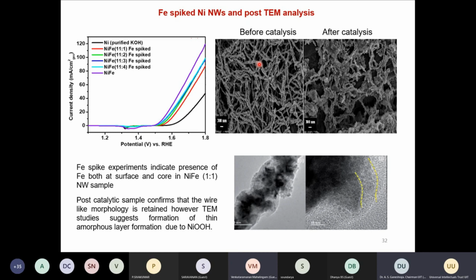But to understand whether the nanoparticle or nanowire morphology changes or not, we have done TEM studies, and what we found is it's not really changed. The nanowire is slightly roughened, but basically the morphology is retained. What we see from the TEM is a slight amorphous layer formation on the nickel wire surface, which is good, which basically improves the activity.